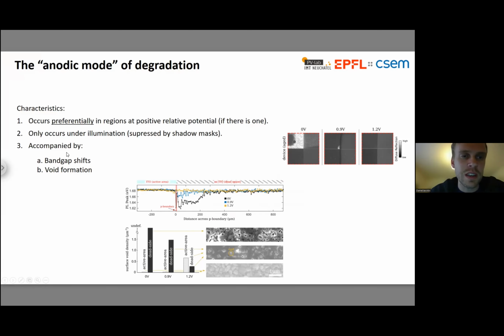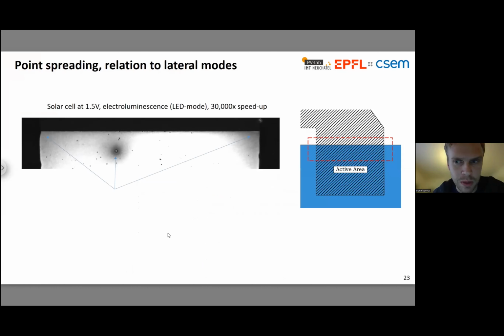The mode seems to be accompanied mainly by band gap shifts in our mixed halide perovskites and the formation of these voids. The void formation is what you're seeing in these diffuse reflection images that I showed on the right. It seems to be reported by more and more people now, so it might be quite a universal feature of perovskite degradation that you have these voids. But the distribution of these voids and their variation with applied voltage is very interesting if you look at the different device regions. I don't think I'll go into all the details of that now, but it's all elaborated in the paper.